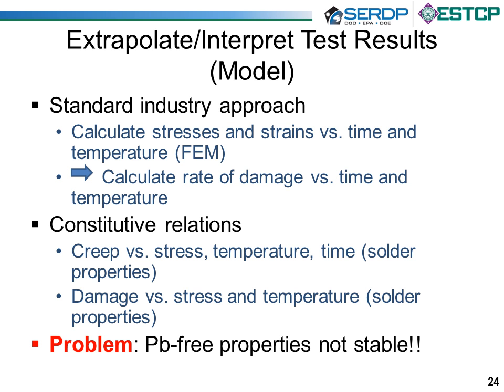These are expressions that tell me what is the creep, the plastic deformation, as a function of temperature, stress, time, and so on. That means I need to know something about the properties of the solder in this case. The other thing I need to know is, if I knew the stress and the temperature and so on, what would be the damage done at a given time by that stress? And again, that's another aspect of solder properties. And that's what we always did with tin-lead solder.